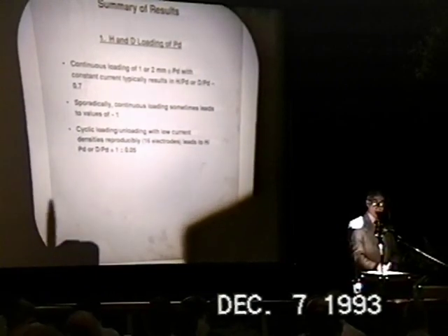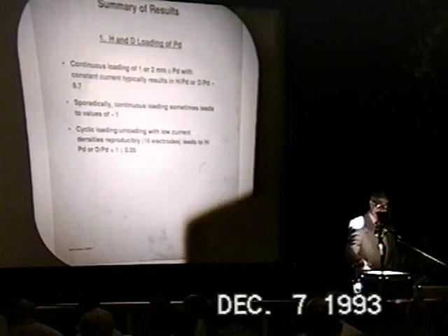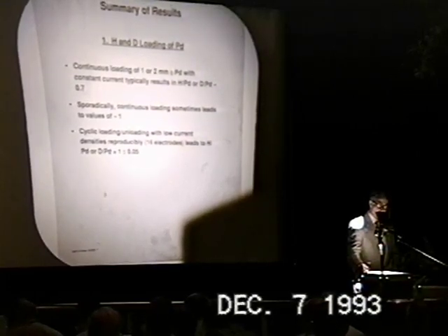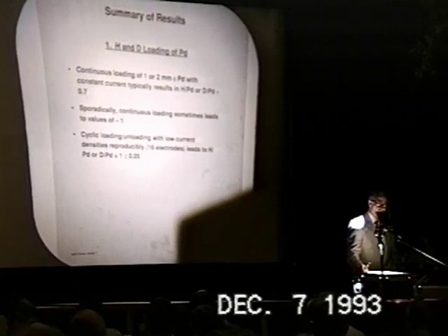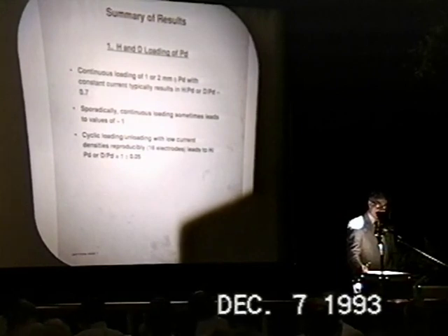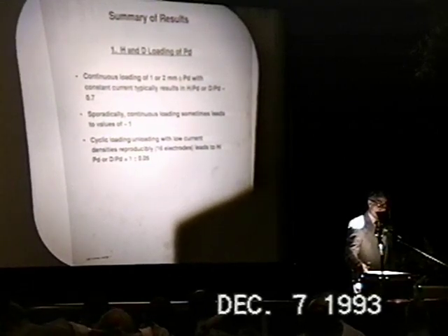We did, however, in every one of these cases, hydride the electrodes, and we gas-loaded the electrodes by subjecting them in a vacuum system to 1 atmosphere of hydrogen or deuterium, which resulted, as usual, in a loading of 0.7. The manipulations on the electrode after gas loading were limited typically to about 3 minutes.